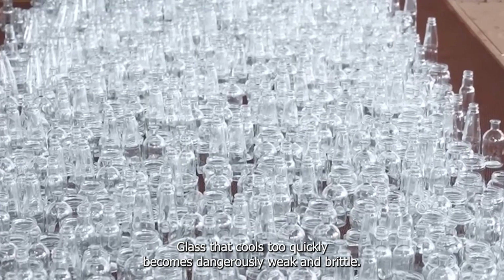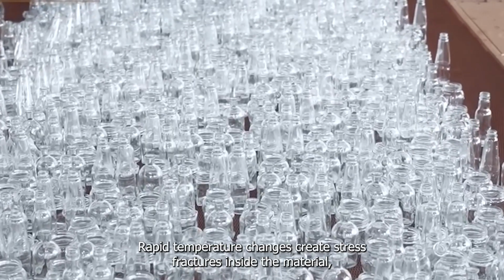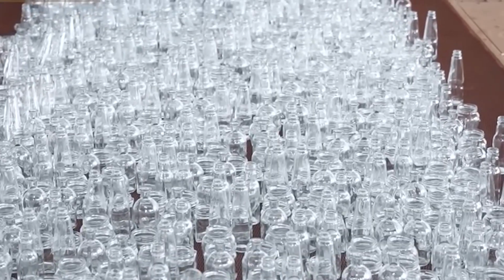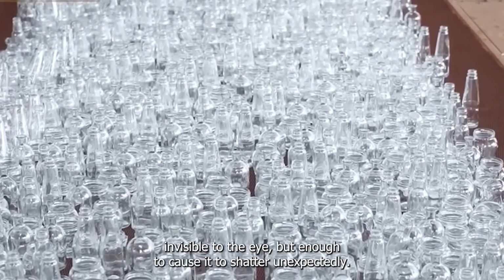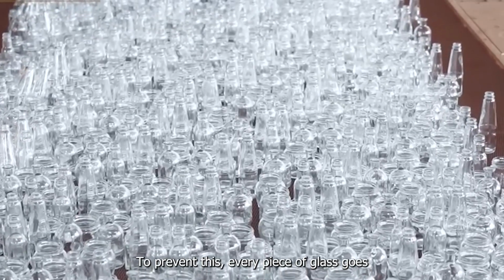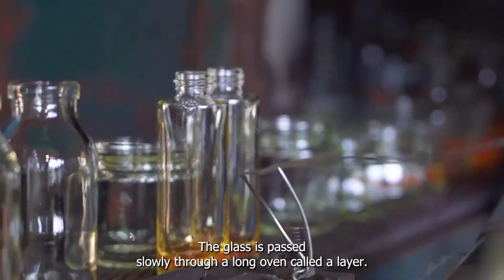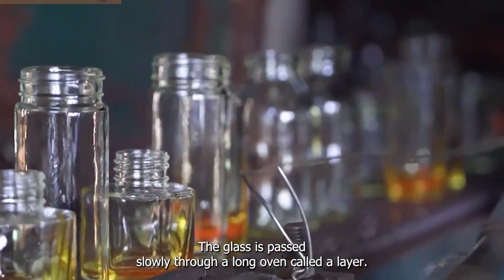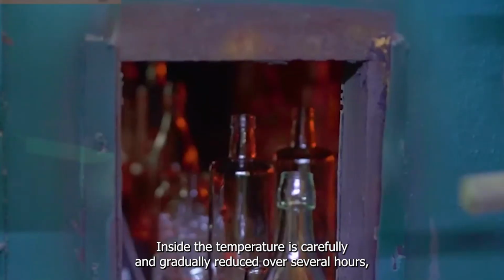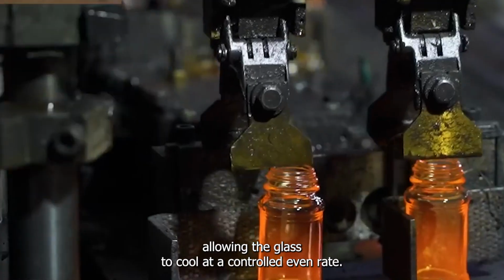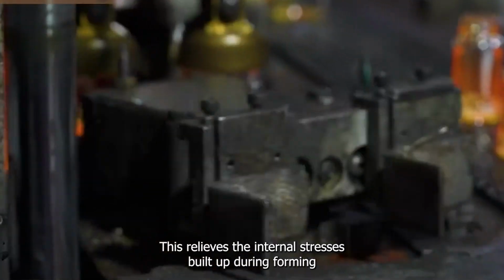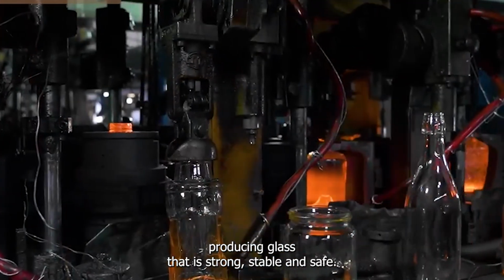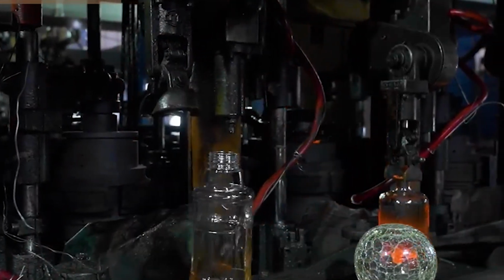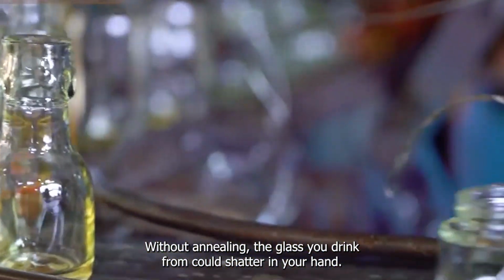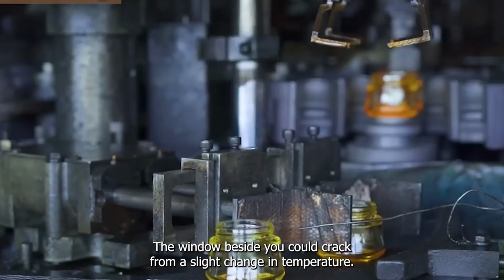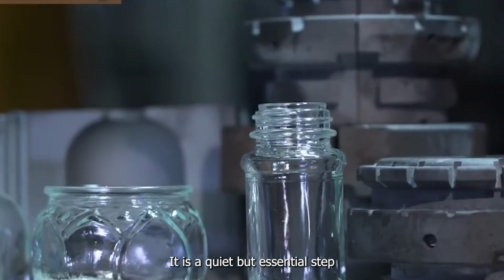Glass that cools too quickly becomes dangerously weak and brittle. Rapid temperature changes create stress fractures inside the material, invisible to the eye but enough to cause it to shatter unexpectedly. To prevent this, every piece of glass goes through a process called annealing. The glass is passed slowly through a long oven called a lehr. Inside, the temperature is carefully and gradually reduced over several hours, allowing the glass to cool at a controlled, even rate. This relieves the internal stresses built up during forming, producing glass that is strong, stable, and safe. Without annealing, the glass you drink from could shatter in your hand. The window beside you could crack from a slight change in temperature. It is a quiet but essential step.